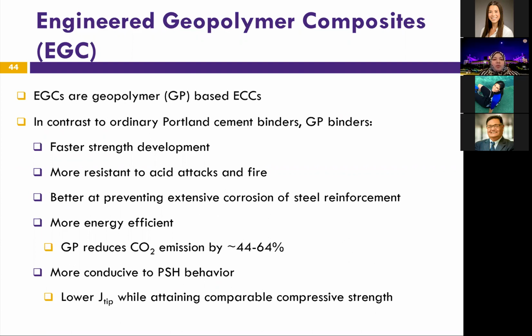So why do we use geopolymers? The reason is geopolymers are better than concrete binders. If we compare them to Portland cement, we'll see that they have a faster strength development because polymerization takes place much quicker than hydration does. And it's more resistant to acid attacks and fire. And it's better at preventing corrosion of the steel reinforcement. In addition, it also has a much lower footprint because geopolymer produces much less CO2 emissions by 44 to 64% when compared to concrete. So why do we use it in ECC?